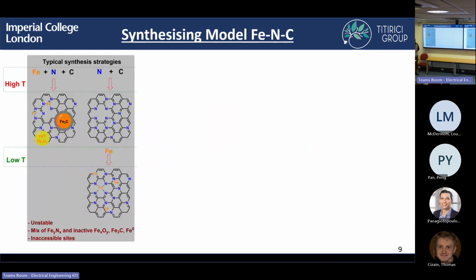And if you want to load more iron in, then you end up having some issues. If you mix your iron, nitrogen, carbon catalyst with a high amount of iron, you'll end up forming different atomic species other than just single atoms. At high temperatures you have carbothermal reduction, so once you go above 600 degrees, you'll be forming, for instance, iron carbides. These are species that we don't really want in the system because, one, we're then not making a model system, but two, these can lead to different degradation pathways and also parasitic reactions. We can alternatively do a high temperature pyrolysis with just our nitrogen carbon and then load our iron at low temperature, but still we're lacking a template for the active site, so we still end up with a distribution of different types of sites.